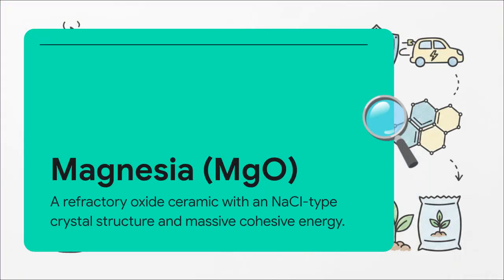Magnesium oxide is what we call a refractory oxide ceramic, and brilliantly, it shares the exact same simple crystal structural blueprint as regular old table salt. You know, that standard NaCl-type structure. But here's the massive difference. MgO has highly charged magnesium and oxygen ions sitting in that lattice, and these create such intense ionic bonds that they impart a massive cohesive energy. It actually boasts a lattice parameter of about 4.21 angstroms, which means its atoms are packed incredibly tight, and it has a massive enthalpy of formation. Essentially, that just means it takes extreme energy to build it, and it's incredibly chemically stubborn to break apart.